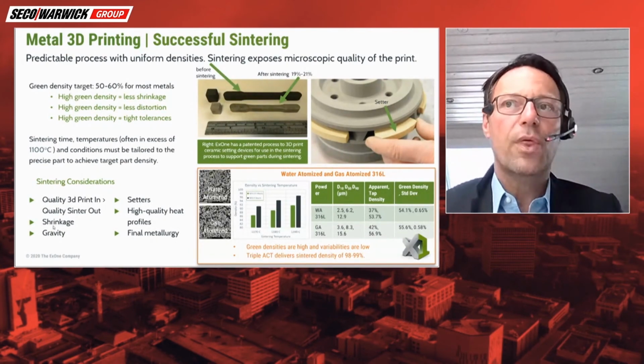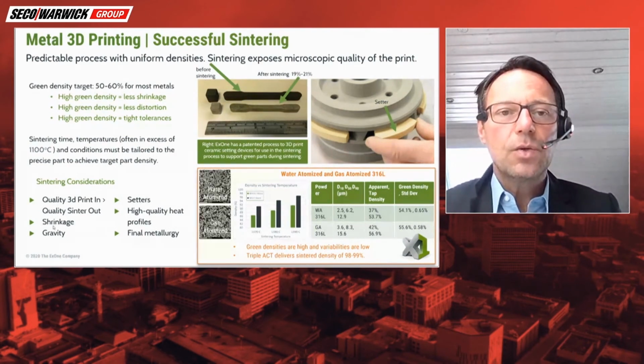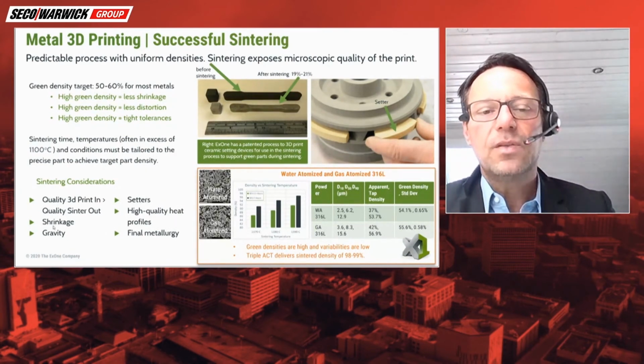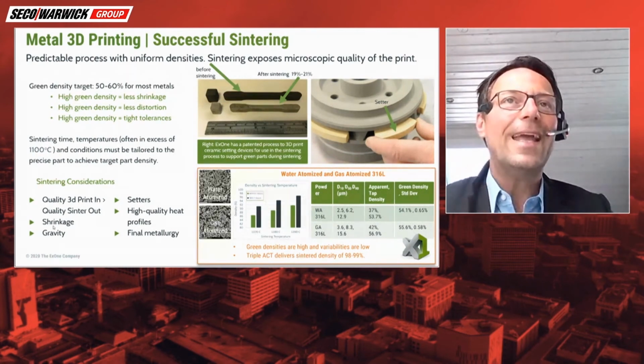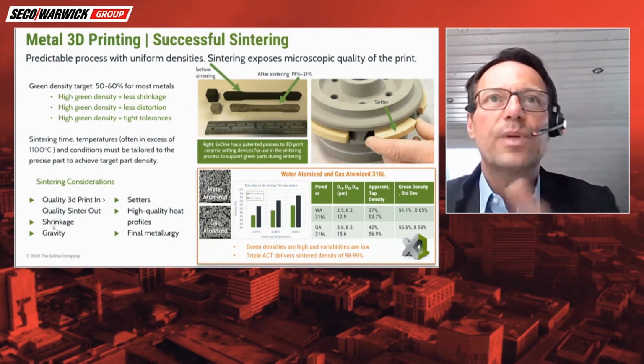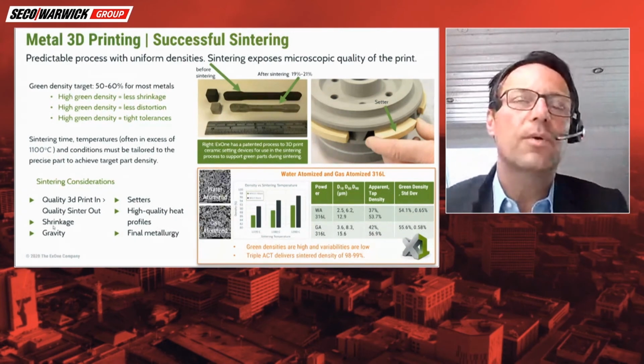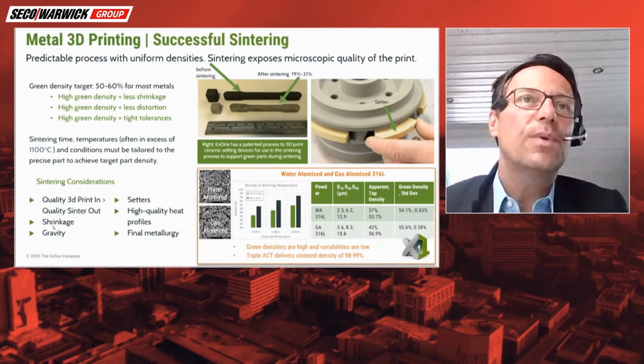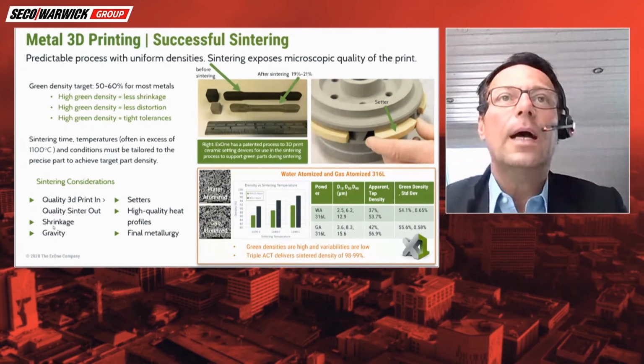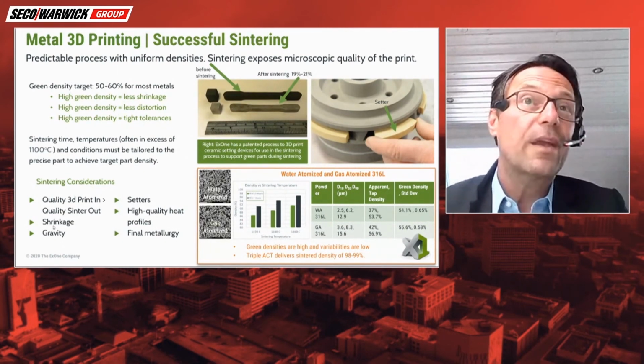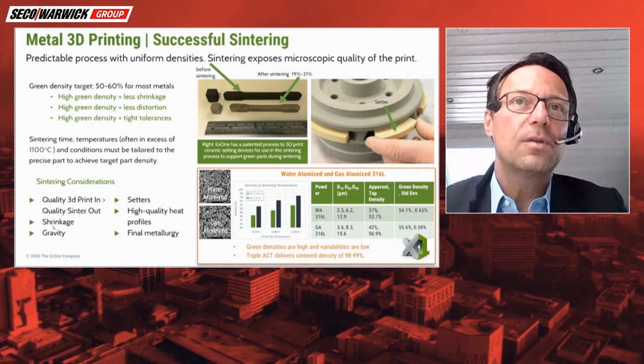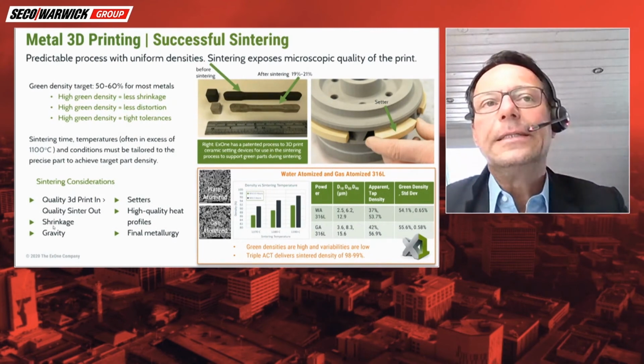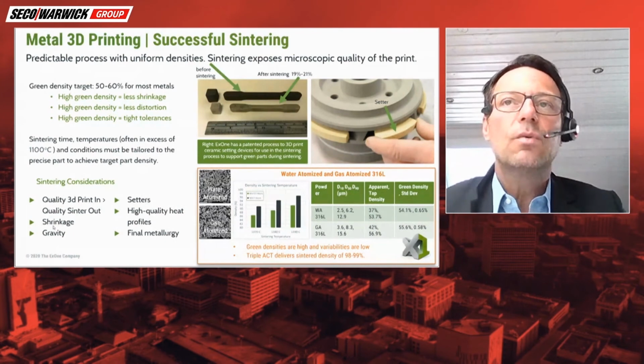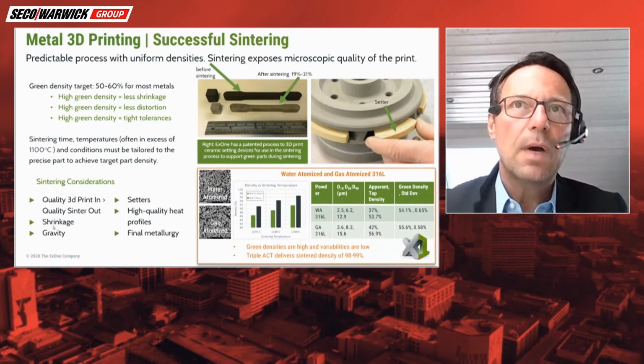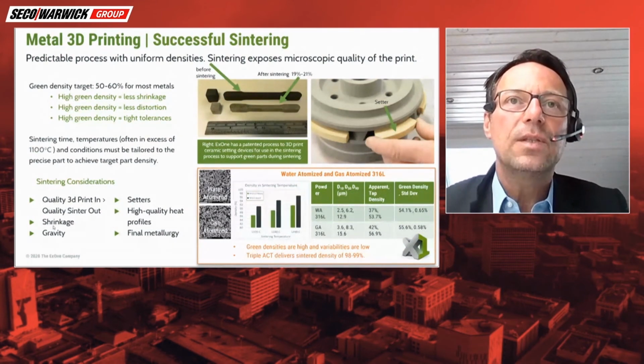Everything that comes along with shrinkage also belongs to how you start, that means how the green part, the green density, looks. And this brings me to the point of why we have decided to go for MIM powders, because there we can reach a higher green density that brings us less shrinkage and, even more important, tighter tolerances and less distortion. On the other hand, of course, you need to consider before you print how that distortion might look while you go through the sinter process.